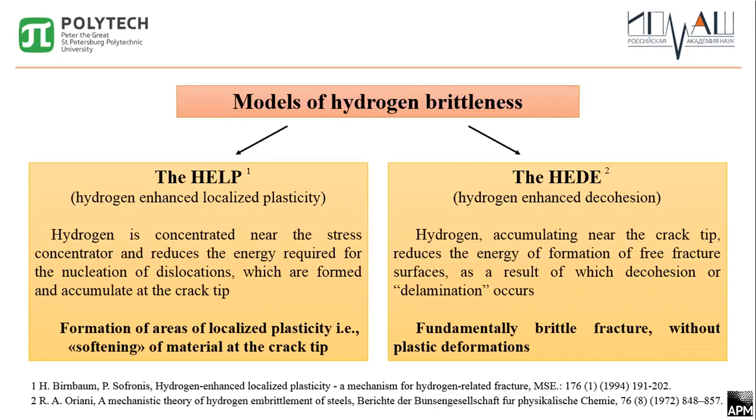It, on the contrary, considers fundamentally brittle fracture without plastic deformation. Its main idea is that with an increase in the local concentration of hydrogen, the energy of formation of new fracture surfaces decreases, the adhesion of the crack edges decreases, and delamination occurs. The development of these models was accompanied by many test experiments, most of which were carried out on samples after artificial charging with hydrogen, usually in an electrolyte solution using a cathodic current.